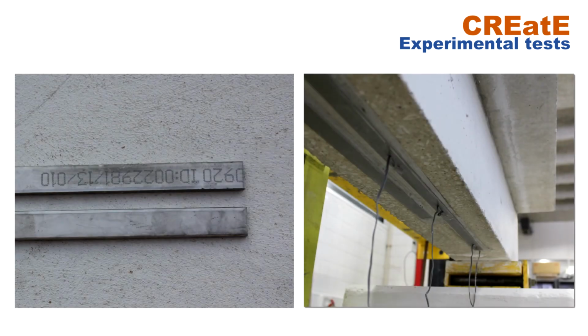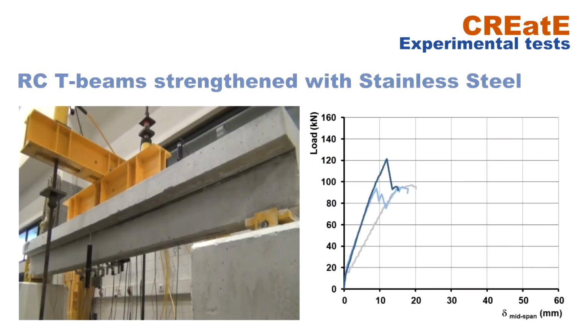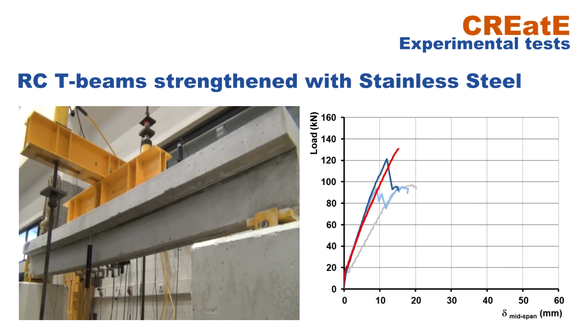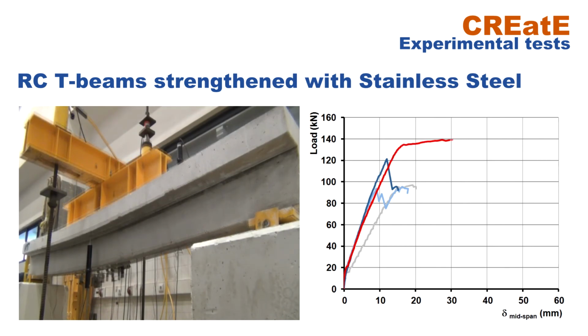The second example refers to the reinforced concrete T-beam retrofitted with stainless steel bars using the CREatE system. The curve of the reference beam is presented in gray, whereas the test curve of the EBR technique is in light blue and the curve of the NSEM technique in dark blue. These curves are compared with the test curve of the CREatE system presented in red in real time. The results show that the stiffness and the yielding force were clearly incremented. The strength was incremented in 50% and the ductility in 270%.